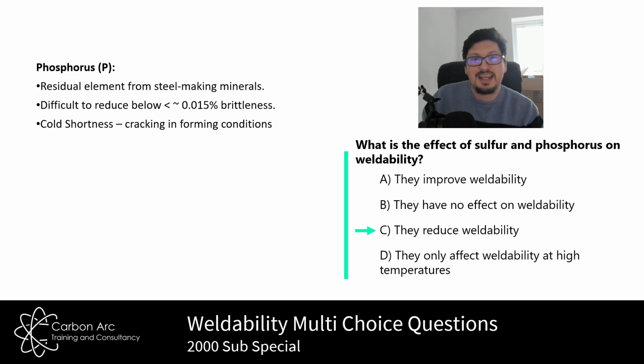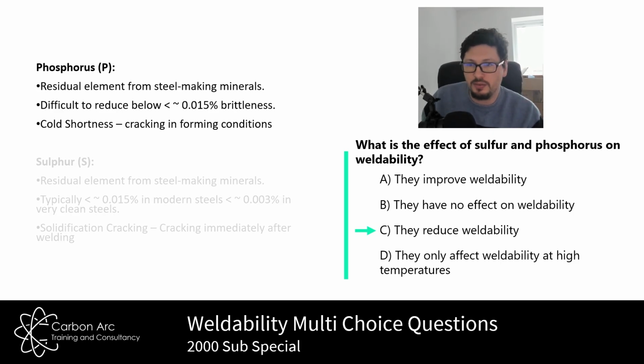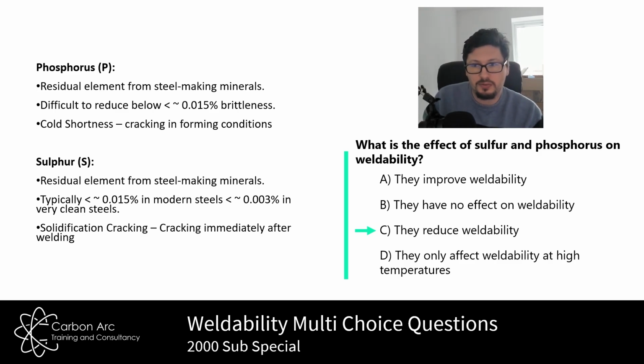Now, sulfur connects into a lot of failure mechanisms in different ways, okay? The most common one we talk about sulfur with is solidification cracking. And again, we try to remove sulfur in weld steels we know we're going to weld as much as possible. And this is where a lot of cost enters the system in steel manufacture to drive the sulfur level down. So sulfur mainly is solidification cracking, but has a play in lamellar tearing and sort of inclusion creation and stuff like that. Yeah. Solidification cracking, lamellar tearing, inclusions, non-metallic sulfur is our issue.